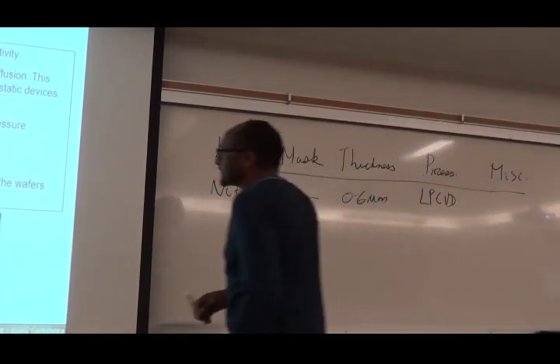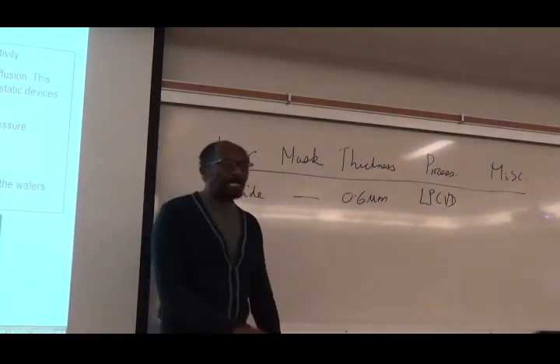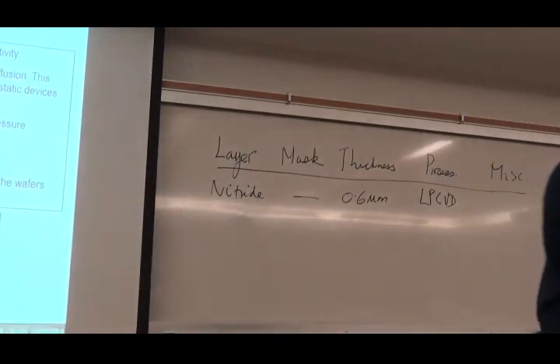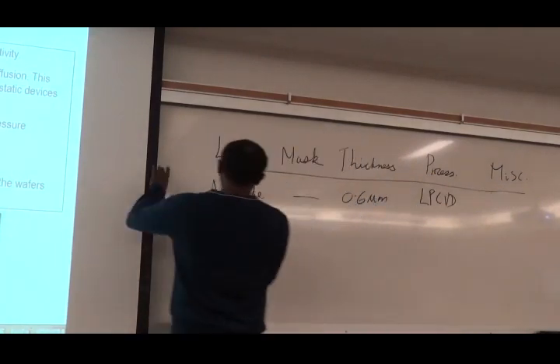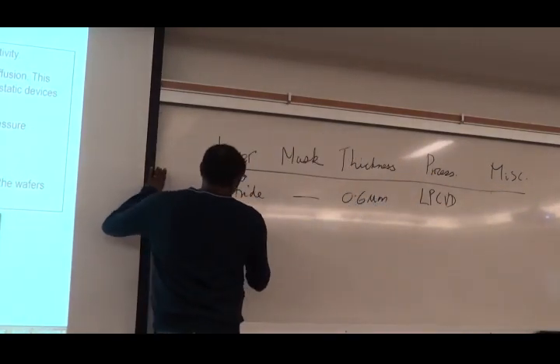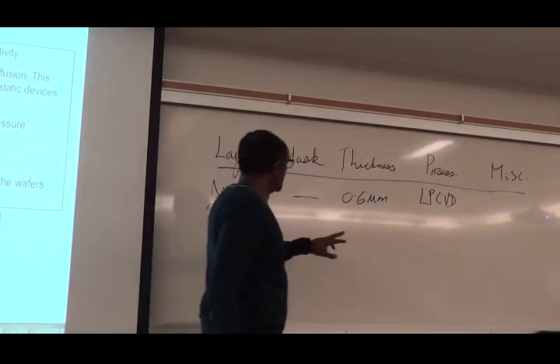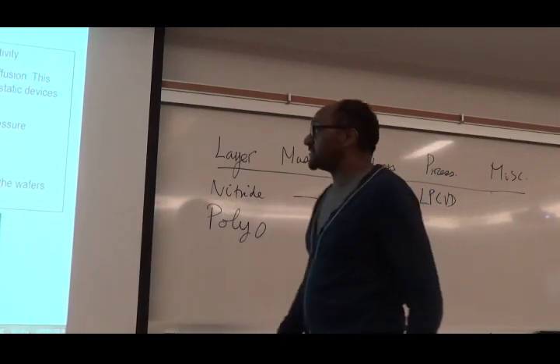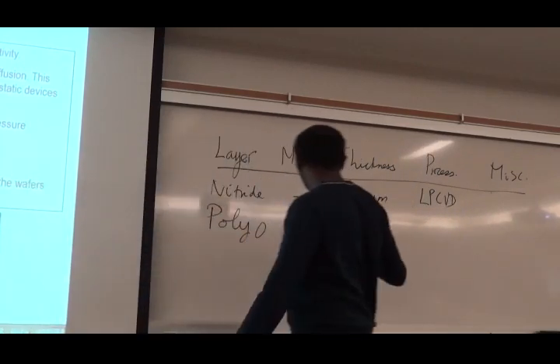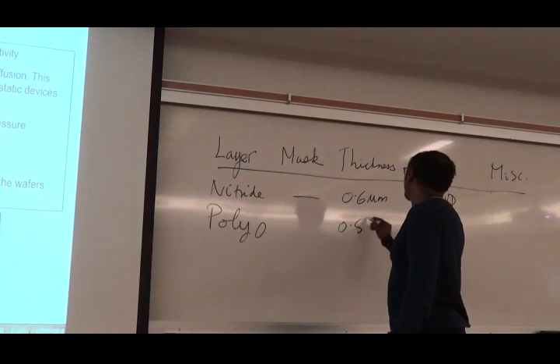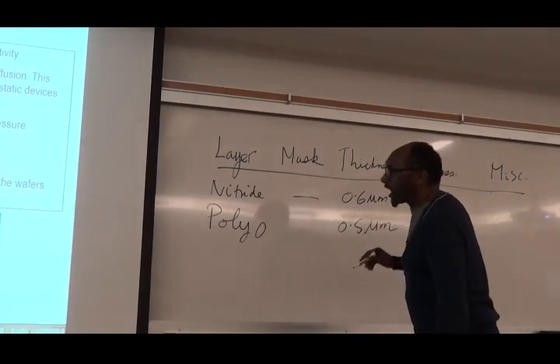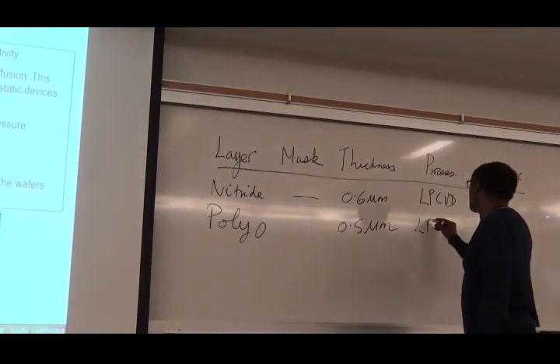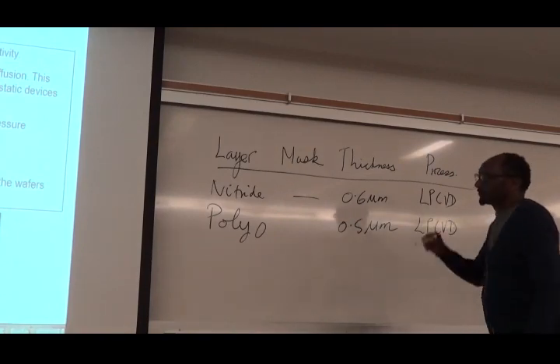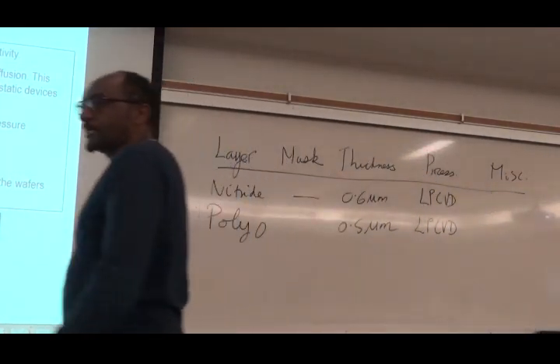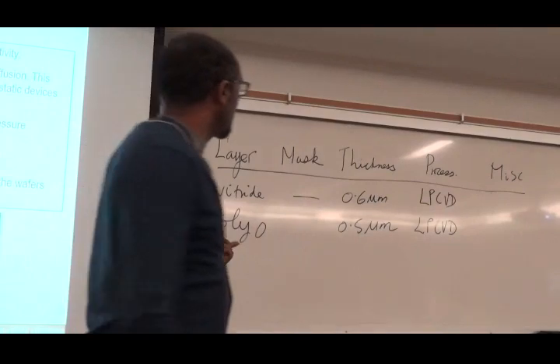Then we deposit our first poly layer, which is poly 0. So layer name here is going to be poly 0. Thickness, it's very thin, 0.5 micron or 500 nanometers. Process LPCVD. Okay, so far so good. Then we pattern it.